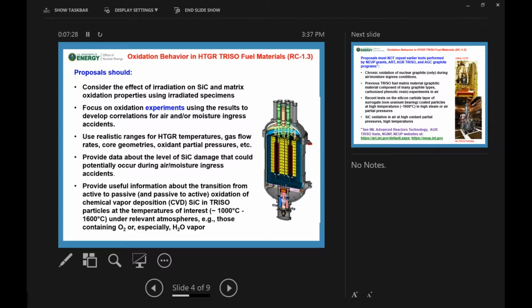So what are the temperatures of interest? 1,000 degrees C up to 1,600 degrees C. And we chose the 1,600 degrees C because that's the depressurization loss of coolant accident. That's the highest temperature we would see in our gas reactor designs. And to use various atmospheres and different partial pressures. So you can do this as a separate effects test and do a parametric study within these ranges.